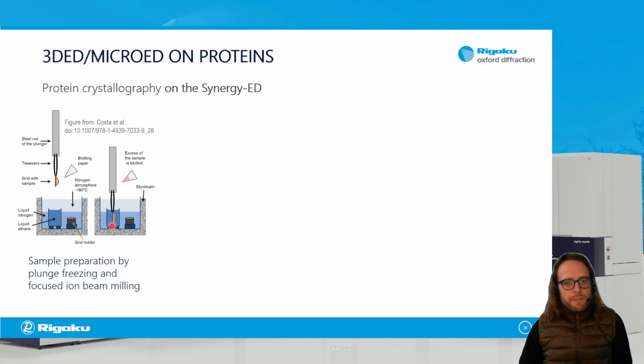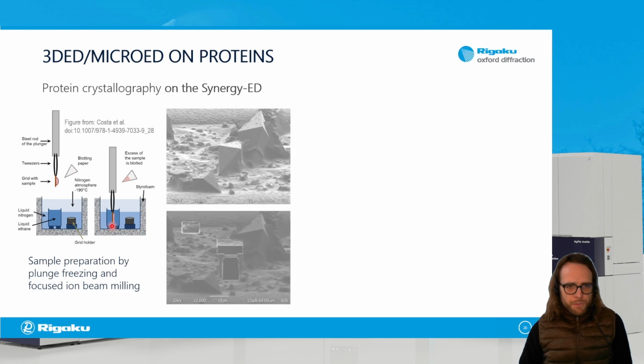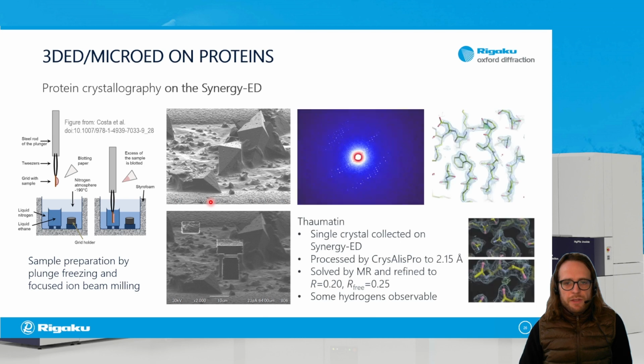And then in the next step, either your crystals there are already small enough, or you can mill them down further using focused ion beam milling. So here you see microcrystals on one of those grids in a frozen state, and you can actually, as seen here, mill a thin lamella out of it, and then insert it into a Synergy-ED. And here's just one of our first example data sets of thaumatin, which we collected up to a resolution of 2.15 angstrom, and then subjected this to our normal processing pipeline using CrysAlisPro and structure solution using molecular replacement.